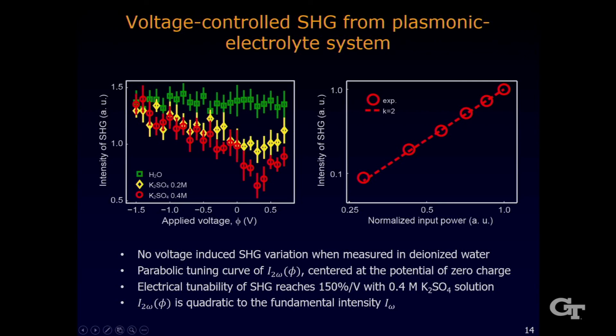For the electrolyte, for example, in this case, I think it's a potassium sulfate, okay? For each concentration, you can see the second harmonic signal varies parabolically with the applied voltage, with the minimum occurring at about 0.3, which is the famous potential for zero charge for this electrolyte system. And the tunability is pretty strong, actually, one order of magnitude stronger than what we have seen in the solid state system, okay, more than 150% per volt in this electrolyte solution.